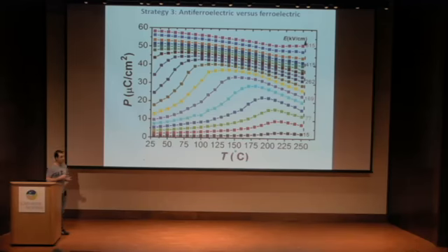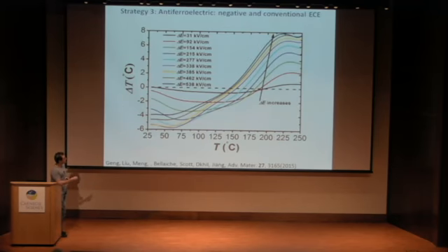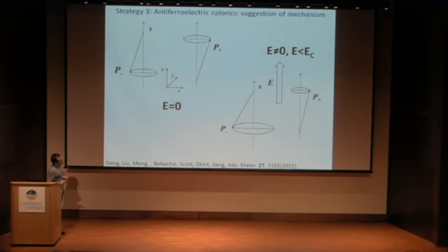And this is very interesting because you can combine negative and positive to enhance the global delta T change of your system. So you see that the value that we got here experimentally is close to minus 5, minus 6 Kelvin, which is a rather strong value of adiabatic thermal change. The explanation was suggested by Jim to try to understand the physics behind this.